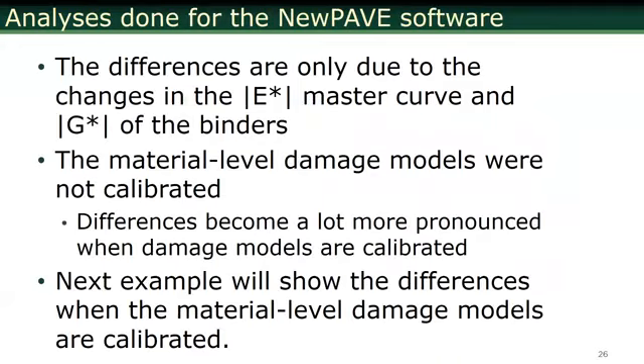I already talked about this. What you've seen in the data so far, the differences are only due to the changes in the E star master curve and G star of the binders. Material damage models were not calibrated for the graphs I showed in the last 3 slides. If you do that, you would probably have a better idea.